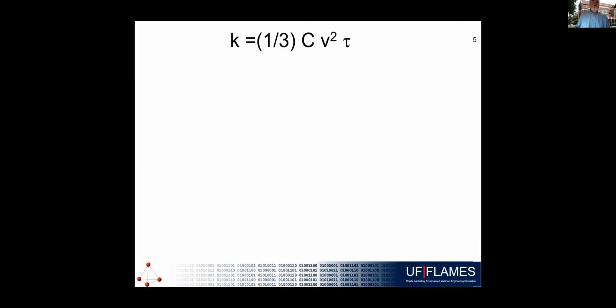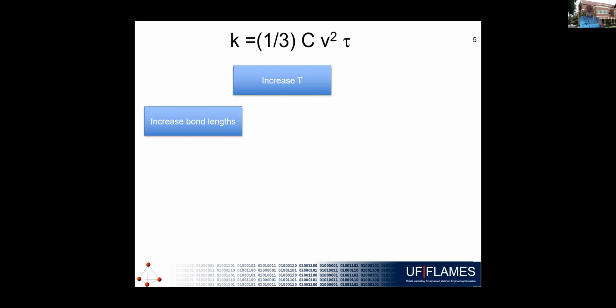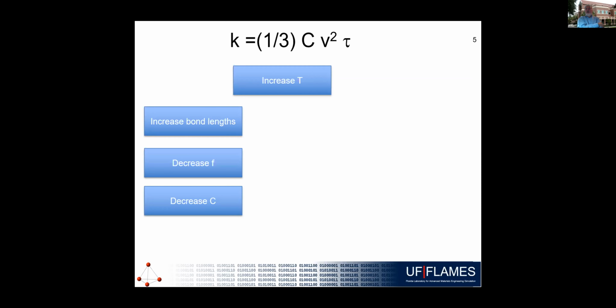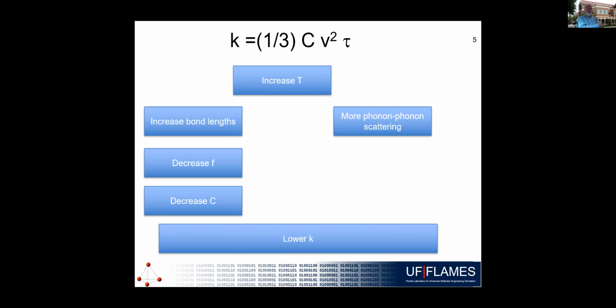So how do we understand these? What approach do we use? This is a version of the standard formula which everyone is familiar with. Thermal conductivity is proportional to specific heat, the velocity squared, and tau, which is the time between scattering events. We use that as our mantra, our baseline for understanding a lot of this kind of work. As we increase the temperature, we increase the bond length, that's thermal expansion. As you increase the bond length, the frequencies of vibration tend to decrease. That decreases the amount of heat carried by each vibration. That was the amount of tea, or coffee, in Professor Snyder's cup going down. And that has the effect of lowering the thermal transport, lowering thermal conductivity.